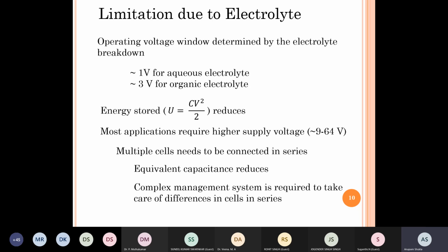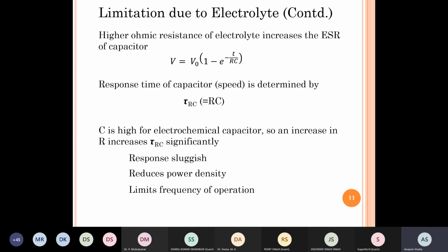So a complex management system is also required to ensure that cells are at a similar state of charge, and when charging is done, it has to be ensured that all cells get fully charged, so that none of the cells are at a lower state of charge, because then during discharge it is possible that these cells may become completely discharged. So these are complications that come because of the lower operating voltage window, which is a limitation brought in by the electrolyte.